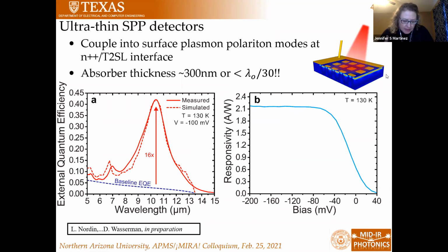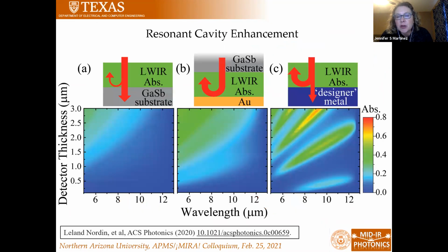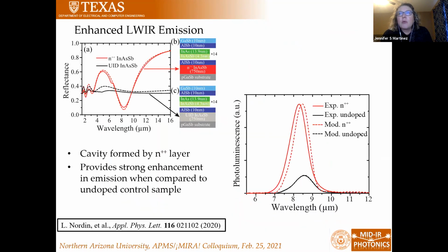Just going back to one of the slides Anas was asking about, where you have the photoluminescence enhancement on the plasmonic surface. What is the distance dependence? Is it still 1 to 10 wavelengths? And how does that fall off for that enhancement? The distance dependence, meaning how far away that plasmonic material can be from your photoluminescent material and still have as good of enhancement, and how does it fall off, basically?